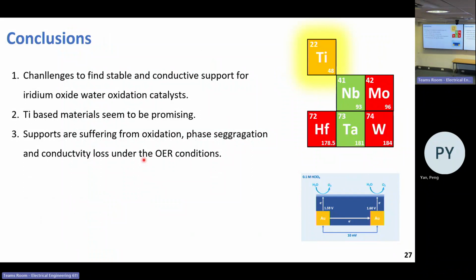So to conclude, it's really challenging to find a stable and conductive support for iridium oxide water oxidation catalyst, because nothing is more stable than iridium oxide itself. Titanium-based materials seem to be the most promising candidate, but they still suffer from oxidation, phase segregation, and conductivity loss under OER conditions.